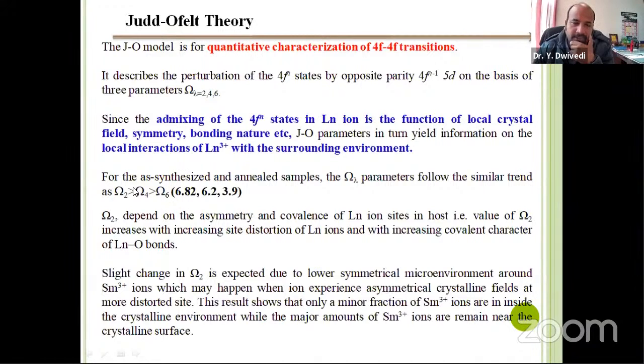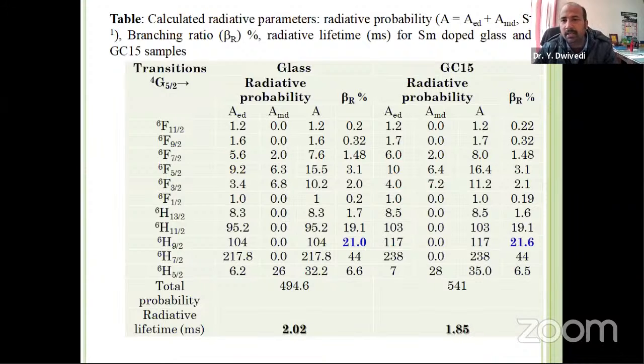So what is the significance of this? Omega 2 value is slightly higher in case of glass ceramics, and this is because omega 2 represents the asymmetry and covalence of the lanthanide ion at its site. In case crystallization is there, even though it looks like samarium ions don't diffuse into the crystal in a larger quantity, most samarium ions remain near the surface, so they are actually in a very asymmetric region.